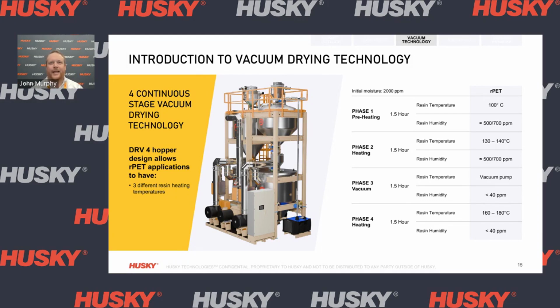Now that I've given you just a high-level overview, I do want to take the opportunity here to go a little bit more advanced and show you everything on the screen here. So this is showing the 4 stages which I just went through on the previous slide. Phase 1, the preheating hopper. Phase 2, heating. Phase 3, vacuum. And then phase 4, post-heating. On the right-hand side, you can see what's going on within each of these phases by showing the resin temperature and resin humidity. So we're heating up to 100 degrees Celsius, and if we consider an initial moisture content of 2000 ppm, we're able to get down to around 500 to 700 ppm in phase 1.